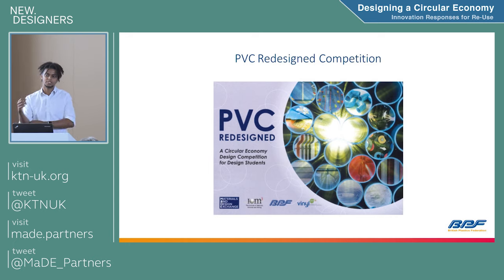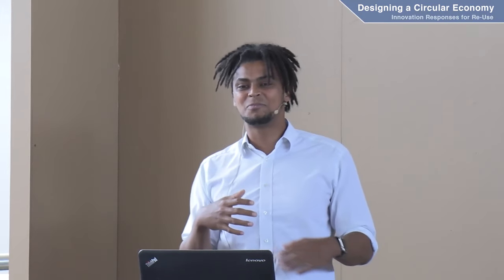About 20 years ago, the industry set up voluntary initiatives to become more sustainable. The first was Vinyl 2010 — establishing recycling targets for PVC and removing questionable additives. Within the EU, there are no lead stabilizers and no cadmium additives used in PVC production. Last year over 640,000 tonnes of PVC were recycled across Europe. Recycling is pretty well established — typically construction products like double-glazed windows, flooring, roofing.